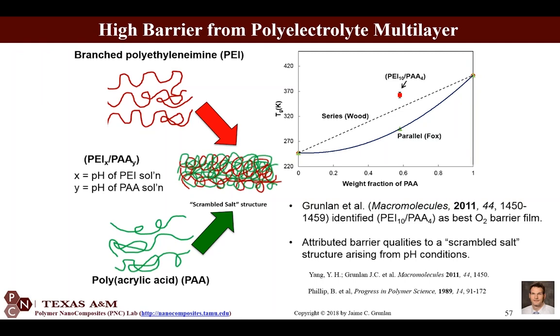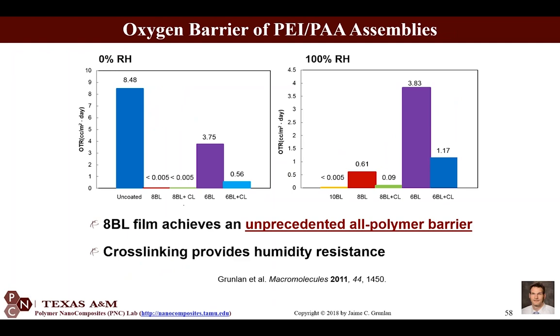So you actually get a higher Tg than even what an upper bound, a wood type of combination of those two Tgs would be. And you also get a pretty high density film, much higher than a typical polymer. So it could be something like 1.3 or 1.4 gram per centimeter cubed. So it's a very unusual interaction, but high, strong interaction between these two polymers. Sometimes it's referred to as a scrambled salt structure, which you could think of as interpenetrating network on steroids or something like that. And it turned out that an 8 bilayer film, I can tell you that's about 600 nanometers thick, had an undetectable oxygen transmission rate.